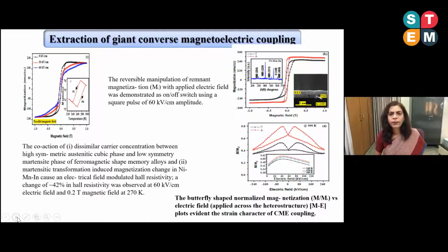Here we tried to see the MH loop at various values of applied voltage, starting with 0 kilovolt, 30 kilovolt, 60 kilovolt, and so on. I'm showing only 3 curves, but we did several measurements with several applied voltages. We were able to see the shift in the MH loop with applied voltage, which established that there is a magnetoelectric coupling between our piezoelectric layer and the magnetic layer.